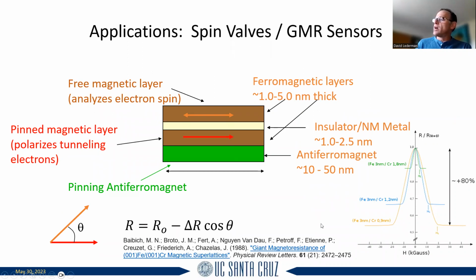So, for example, when you're talking about giant magnetoresistance, which has to do with the fact that the resistance of two ferromagnetic layers separated by an insulator or a non-magnetic metal can change by a significant amount, in this case 80% in iron chromium, when this goes from being anti-parallel to parallel. If you wanted to use this as a sensor or as a data storage device, then you want to keep one of these layers from reversing. And to do that, you can put a pinning antiferromagnet here, which would keep this from reversing, because now the entire loop has an additional bias, if you will.